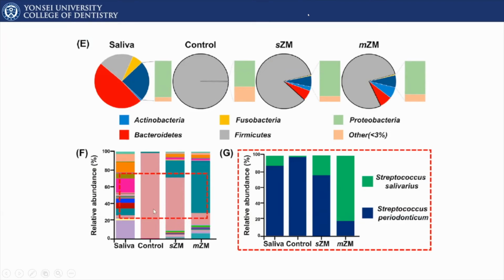You can see here, there is a very low abundance, with just a single or a few bacteria remaining, because obviously we have bactericidal effects. But with these zwitterionic materials, especially the multiple zwitterionic materials, the variety is preserved, and with the multiple zwitterionic materials it somehow even increased. We don't know why, but perhaps this is because the zwitterionic materials are not bactericidal. They are just preventing bacterial attachment, and they also have some positive effect with the ion release. Some sort of ion releasing effects are interacting with microbiomes and therefore being more microbiome friendly.